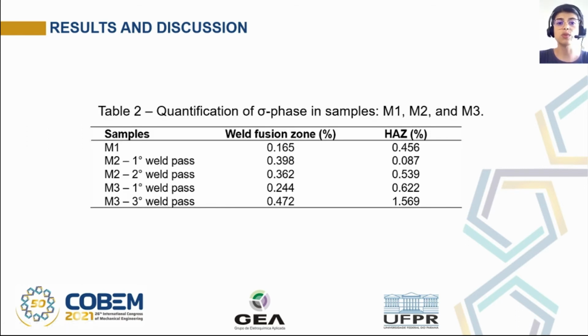Table 2 shows the quantification of sigma phase in the samples in the weld fusion zone and HAZ. As we can see, the sample M3, which has three welding passes, presents more sigma phase in the weld fusion zone and at the HAZ.